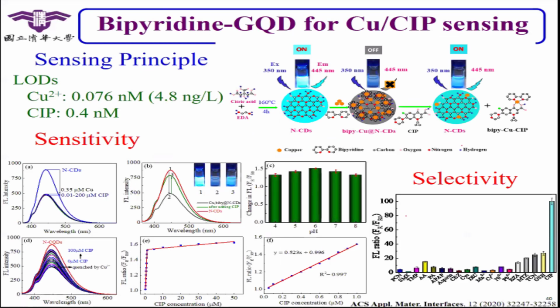We can still use this carbon dot or graphene quantum dot to detect copper, or some antibiotics like CIP. When you use the graphene quantum dots to detect copper, the detection limit will be around 4.8 ppb. This value is more sensitive than AAS and very close to ICP-OES, so that is quite good. We can also use this to detect CIP, a kind of antibiotic used in our food.